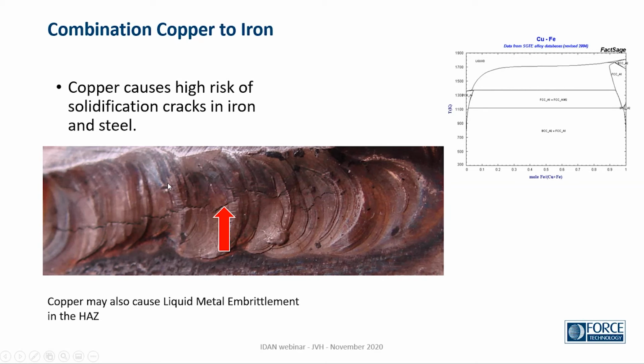In fact, it's a sample that I've had made myself. It's a steel plate with another small part of steel on top of it, and between those two, a 1 millimeter sheet of copper, and welded together, we get these nice cracks. A question? No. Okay.